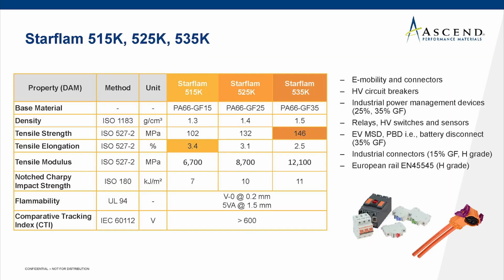And here we show the breadth of our glass fiber loadings. So we have anywhere from 15% to 25 and 35%. In the middle column is our workhorse product, the 25% grade, which applies to the majority of applications, including high voltage circuit breakers, relays, high voltage switchers, and sensors. But if somebody's looking for higher elongation, a little bit more ductility, the 15% grade would be the better choice. And this is useful for industrial connectors, as well as folks like to use the H grade there where they require a little bit better thermal stability.